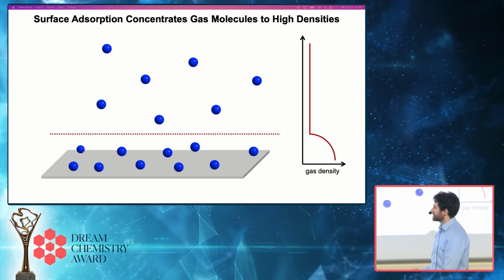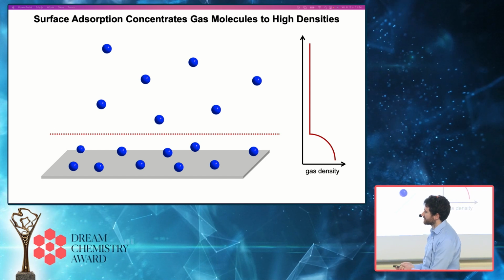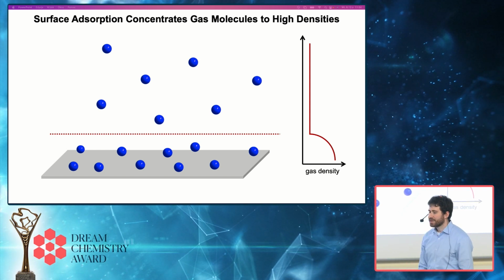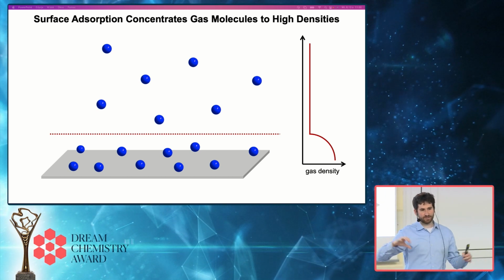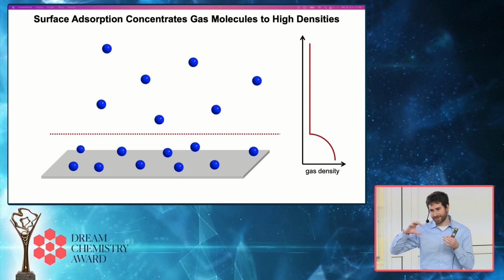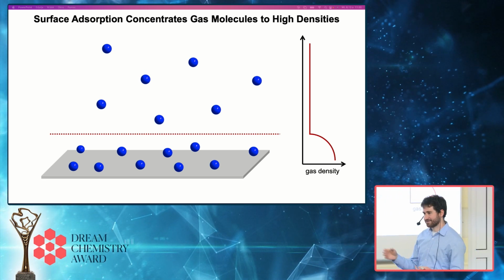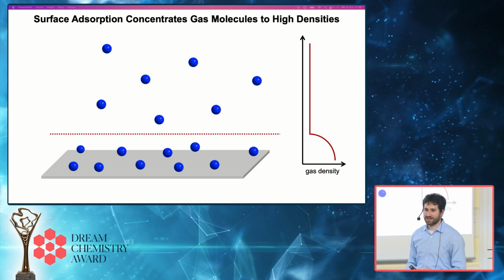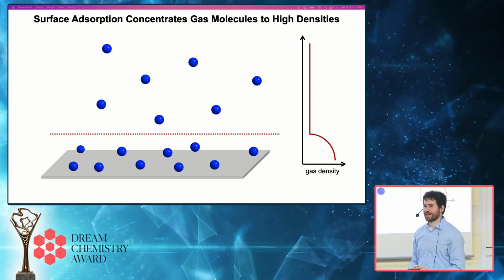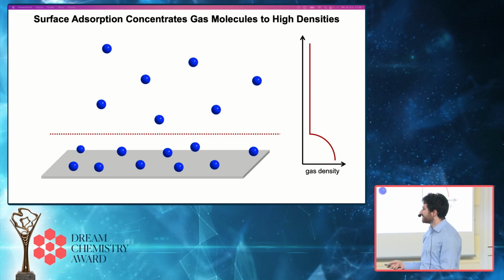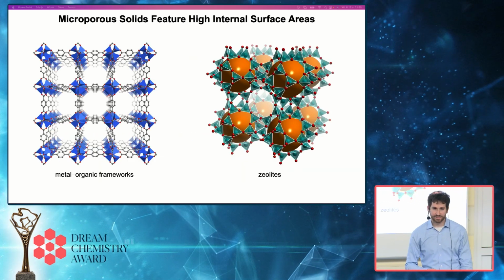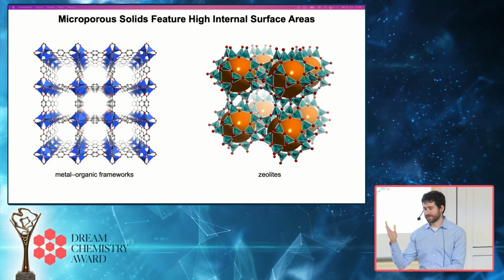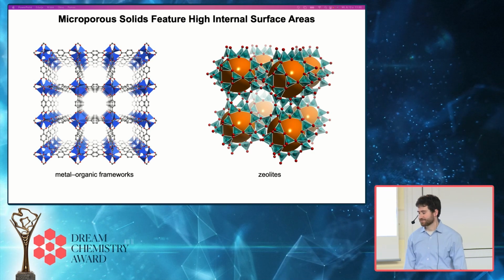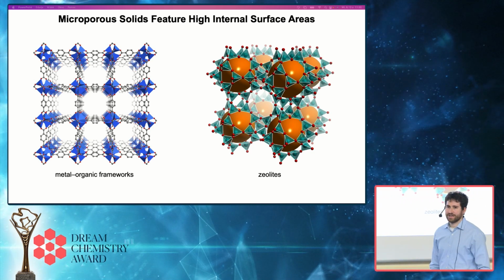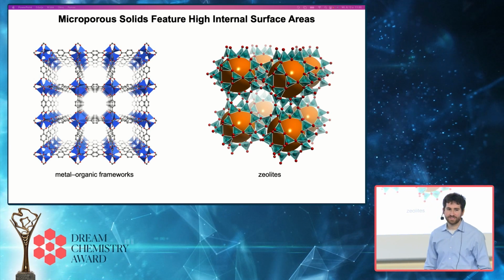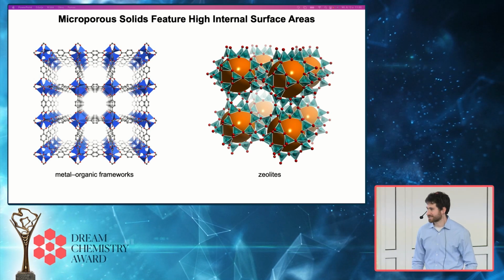And so when you think about surface adsorption, there'll be an increased density of gas present at a surface compared to the bulk phase gas density. This is true for a large surface. It's also true for the internal surfaces of materials. If you imagine folding up a surface to sub-nanometer dimensions inside a material, you can have a large amount of surface able to interact with gas molecules, which can significantly increase the local concentration of gases. And this is why microporous materials like the metal organic frameworks that Carl very nicely introduced in his presentation today are very good at concentrating gas molecules to high density, and why they've received a lot of attention for gas storage and separation applications in the solid state.